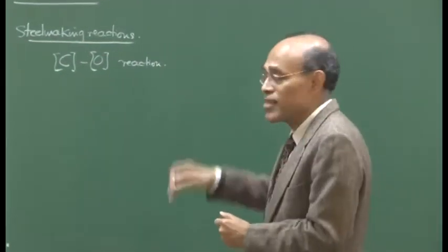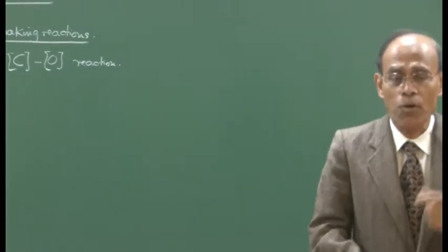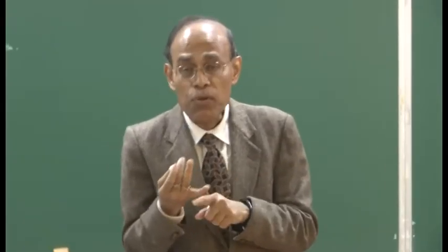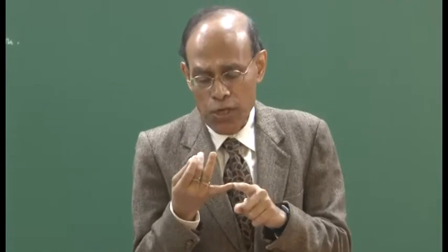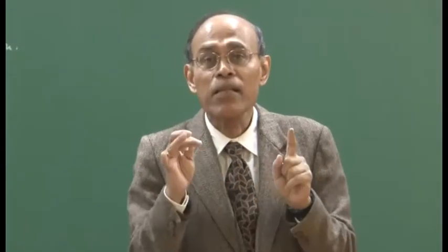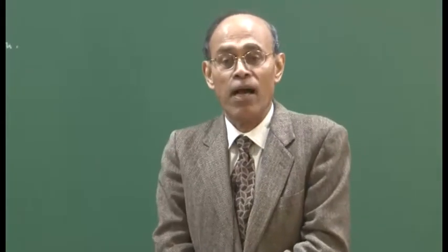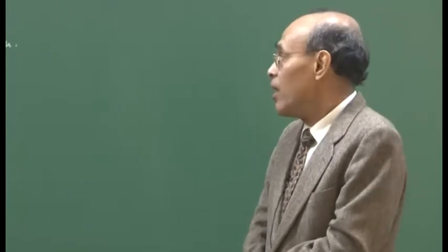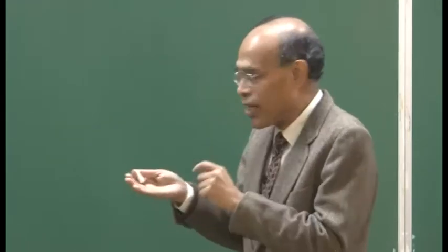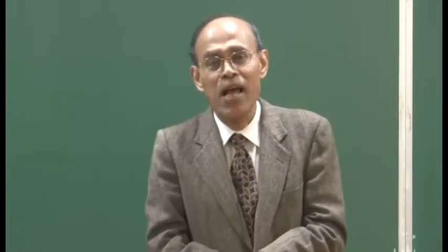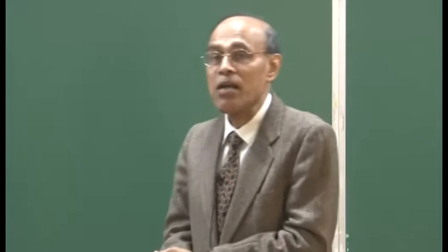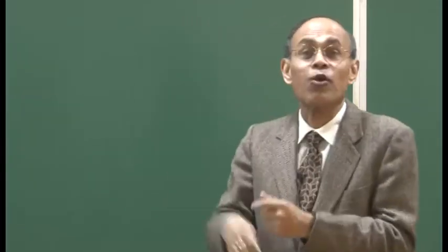We will discuss a series of reactions, because we remember from our knowledge of iron making that we have carbon, silicon, manganese, phosphorus as well as sulfur, which are the principal impurities present in hot metal, and we now need to drive these out. As I have mentioned repeatedly, oxidizing refining, or steelmaking, is the way to drive these elements out from steel. Now, manganese is not so important. Manganese actually is desirable, so that is a little bit different. So I will not rate manganese per se as an impurity, but other elements like carbon, silicon, phosphorus and sulfur need to be controlled to a large extent.